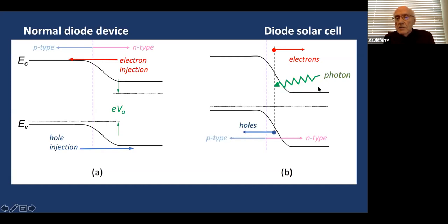And if the photon gets absorbed out here in this contacting region, you create an electron hole pair, but they don't separate because there's no force to separate them. So they have to diffuse to the depletion region, and that's not minority carrier diffusion, that's ambipolar diffusion. And so it's a different diffusion mechanism and has a different speed at which the particles diffuse. But if they can reach the depletion region before they recombine, they can separate.